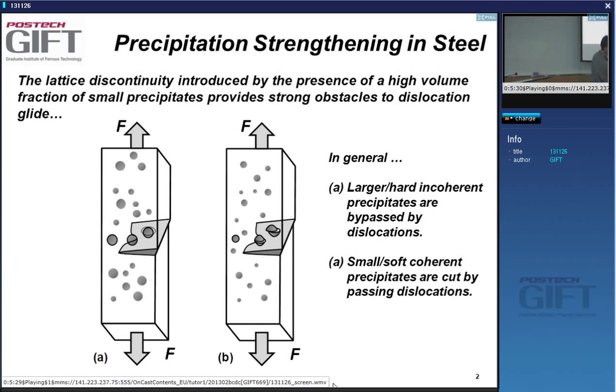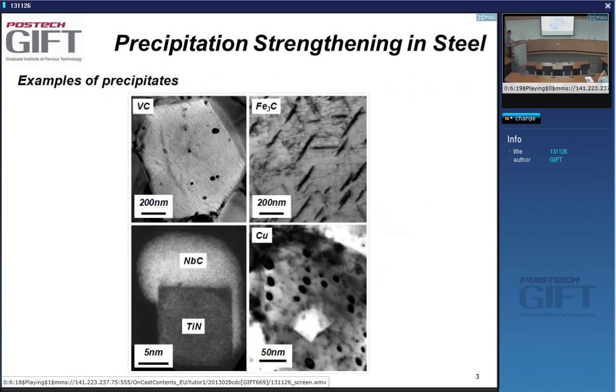So, and then if we go back now a step to this bypassing mechanism, yes, lack of coherency between the particle and the matrix can also be a way to force dislocations to bypass the particle. So we have basically two extremes to these pictures: large or hard or incoherent particles, or particles that are all these things at the same time, or we can have small, soft, coherent particles that can be sheared as the dislocation passes. Okay, and